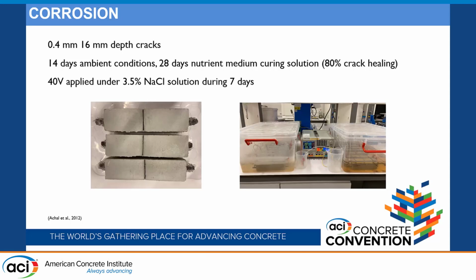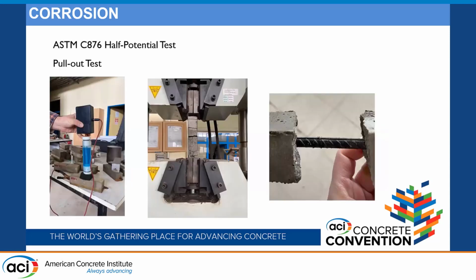In that corrosion setup, we applied 40 volts of electric supply. We connected the electric supply to the rebars in the sample, and we submerged our sample in 3.5% sodium chloride solution for 7 days. Unfortunately, this part of the study was unsuccessful, so we didn't observe any corrosion. First, we tried the half-cell potential test. It says that our samples containing bacteria were corroded, but when we applied the pull-out test, we didn't observe any corrosion, and also our rebars didn't yield from the crack place.